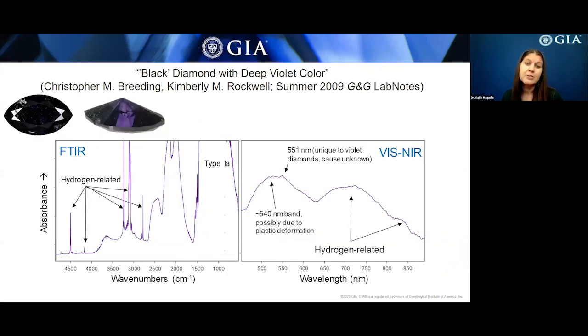Here, we show some of the advanced testing results for the black diamond. Its FTIR spectrum shows it is type 1A with very high concentrations of nitrogen and hydrogen impurities. It creates two strong bands centered at about 520 and 700 nanometers that combine to produce a violet color. The absorption bands were especially strong in this diamond, leading to the face-up black color. In the decades since this stone was submitted, we've seen very few such fancy black diamonds.